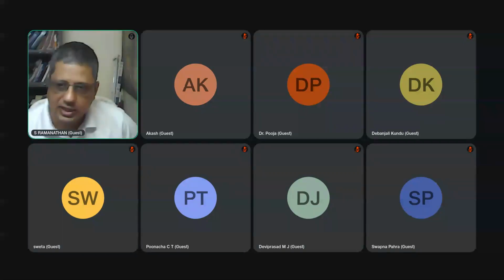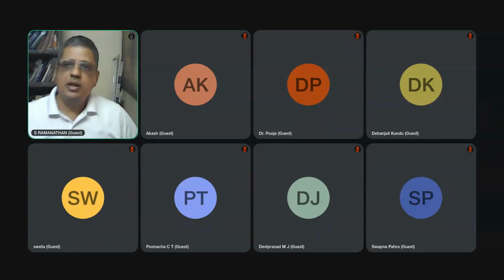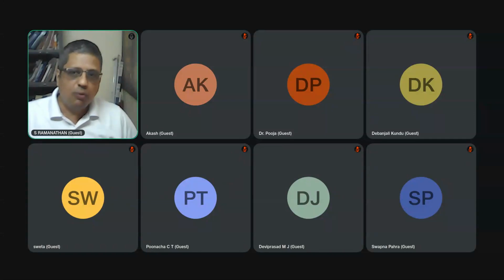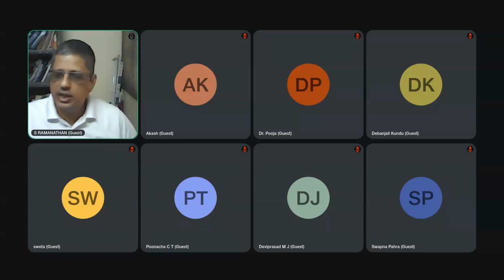Any other counter electrode instead of platinum electrode? Yes, you can use. It depends on the system, right? You can use carbon as a counter electrode, provided that it is not attacked, or if it's attacked, the product goes out as carbon dioxide, and you don't have an issue. You can use gold as a counter electrode. You can use nickel as a counter electrode. Depends on the system you are using.